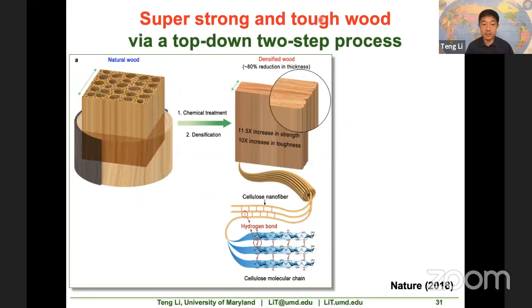We do two steps. In the first step, we do a chemical treatment. There are three compositions in natural wood: cellulose, lignin, and hemicellulose. The chemical treatment partially removed the lignin. Lignin is the component that gives the natural wood its rigidity. By partially removing the lignin, the wood becomes soft. And then we perform the second step, which is a densification process.